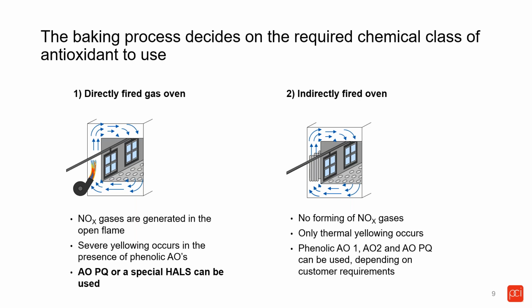And those, as I mentioned earlier, really cause severe yellowing in the presence of a phenolic antioxidant. In order to overcome this yellowing, the AO PQ, the one we talked about earlier, has really good performance to prevent this yellowing. But there are also some HALS, and that is also quite interesting, some hindered amine light stabilizers that can also be used as a gas fading stabilizer. And that's what we will see. So again, when there is no NOx formed, or it's what we call an indirect gas oven, any antioxidant can be used, and obviously it will make more sense to go to a phenolic antioxidant because of the cost advantage of such a stabilizer.